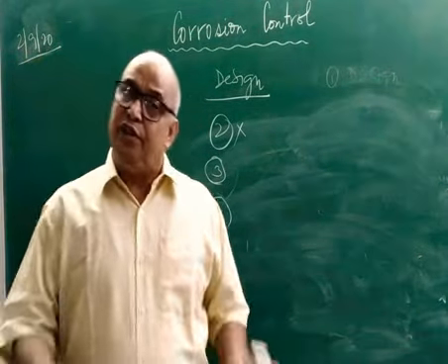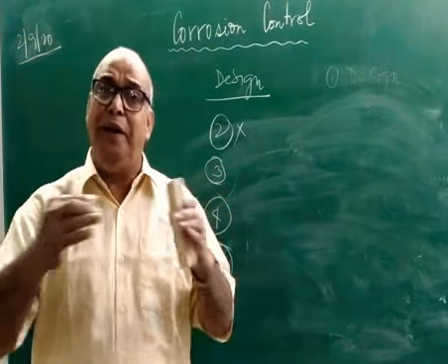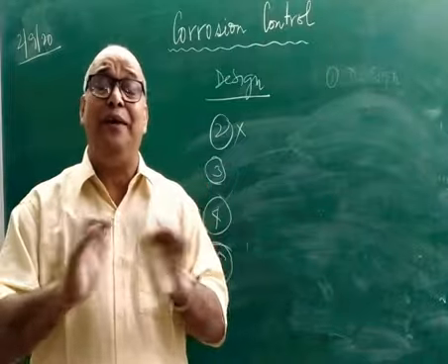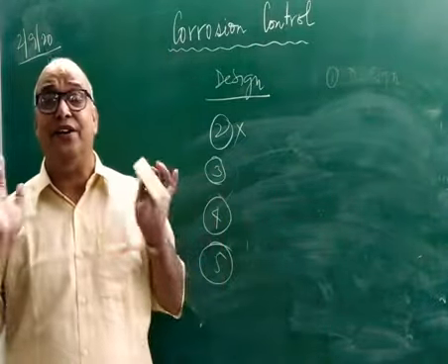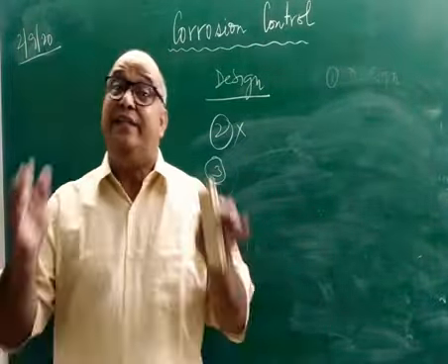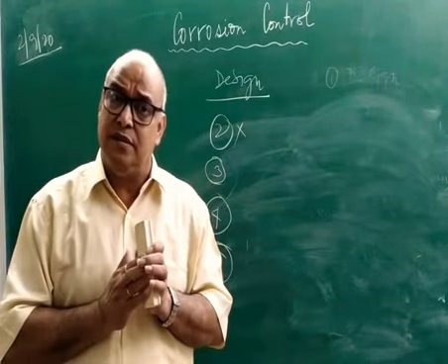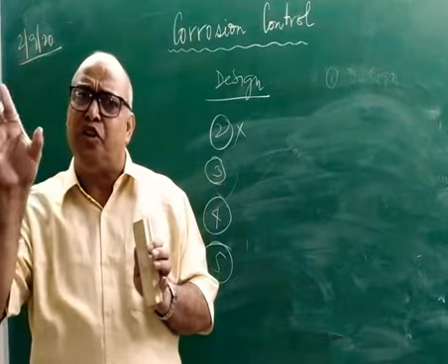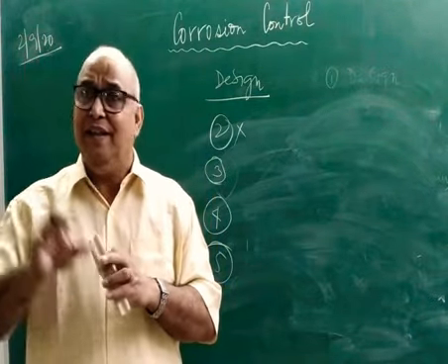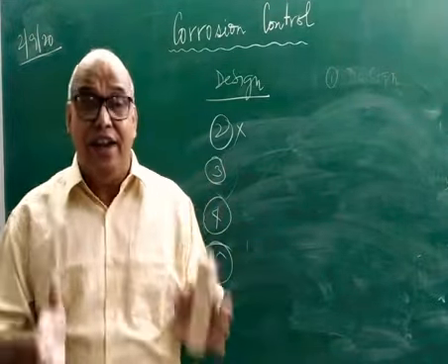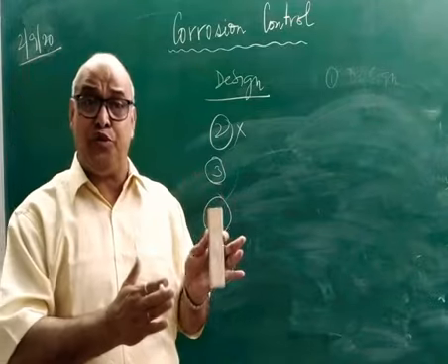Another situation may be there. Suppose we have to use 2 different types of metal, they will be in contact, and they are not giving you a larger anodic area. In that situation, what do we do? We will propose a design where we choose 2 different metals holding very close positions in the electrochemical series, so that the difference of their electronegativity or electrode potential will be minimum, and the intensity of the electrochemical cell being produced will be minimum.